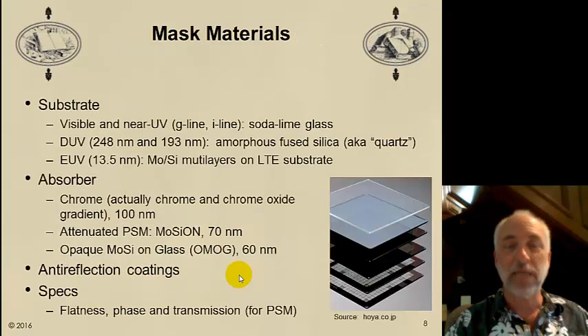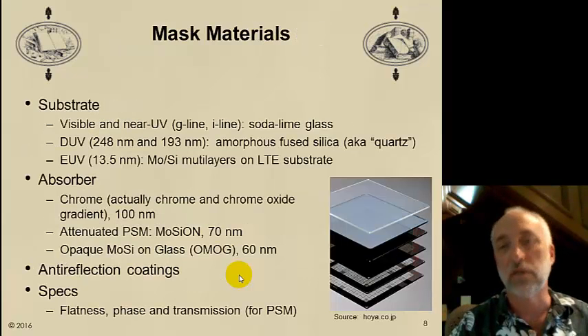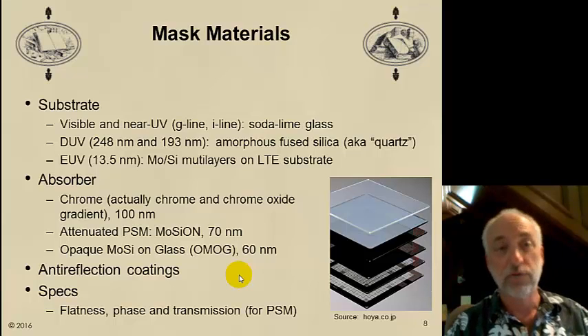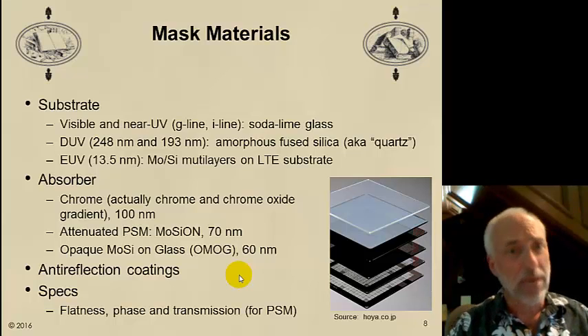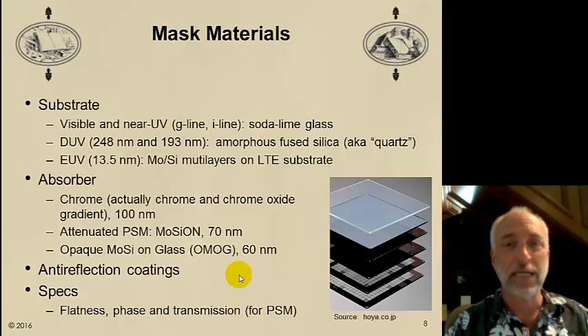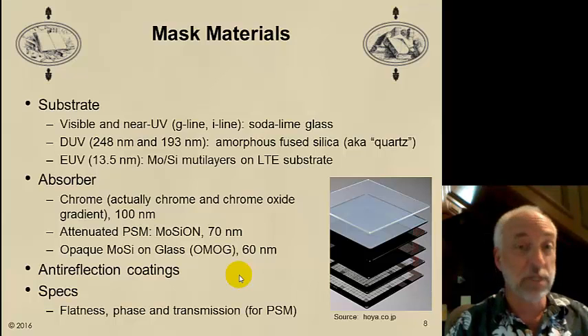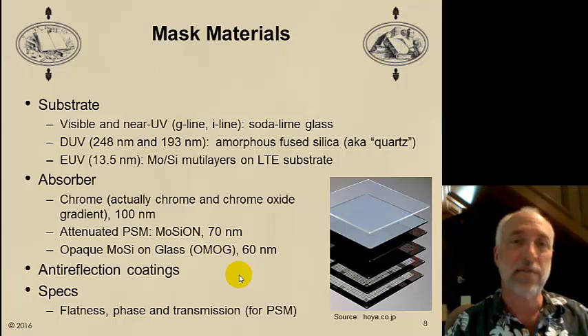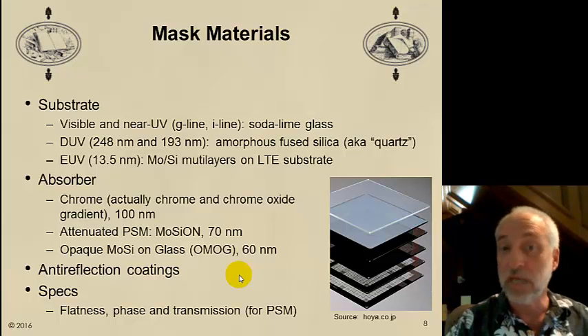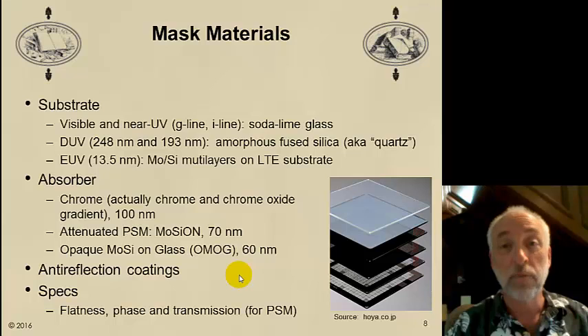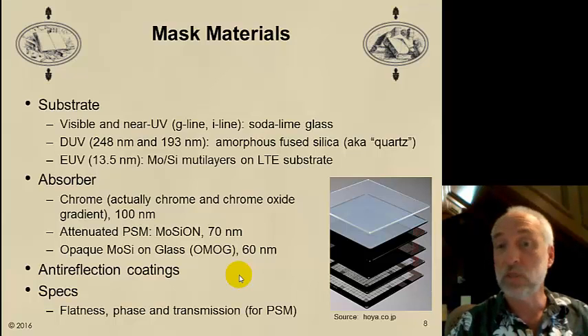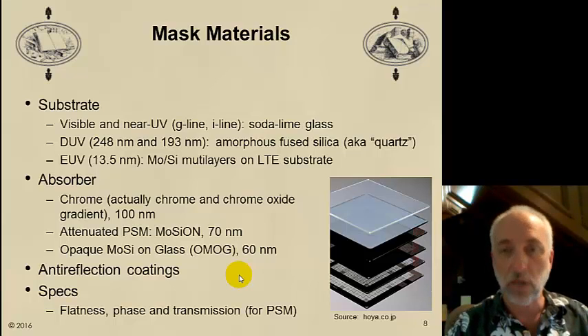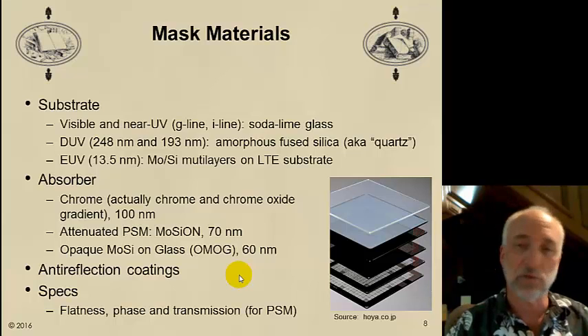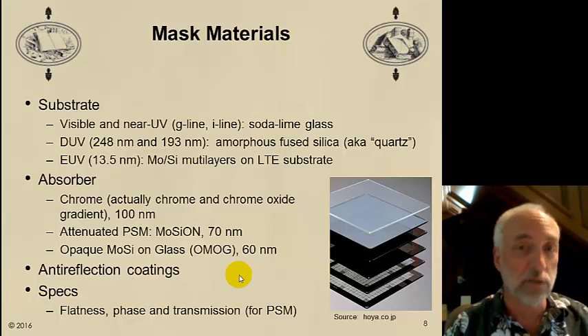Well, that's the mask making sequence. Let's look at the materials that we use to make these photomasks in a little bit more detail. First, the substrate. Back in the days of G-line and I-line lithography, where we had visible light, 436 nanometer wavelengths, or near UV, the I-line, 365 nanometers, we were able to get away with some fairly simple glass like soda lime glass. That's the kind of glass we use for our plate glass windows in our homes.